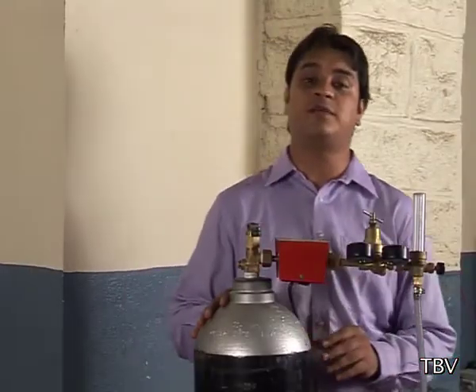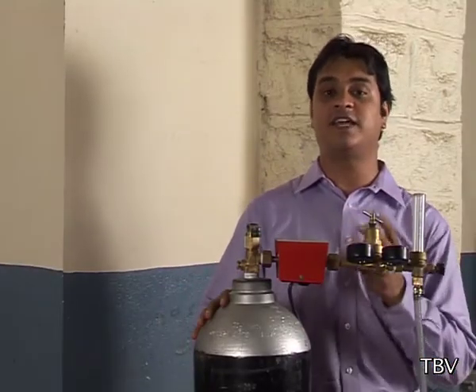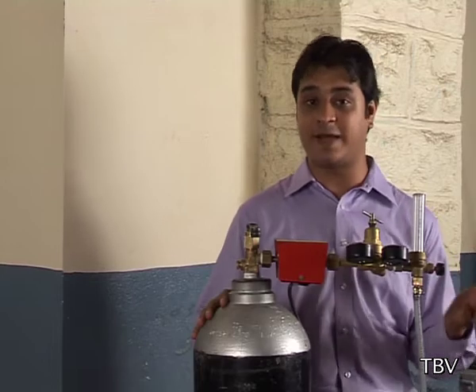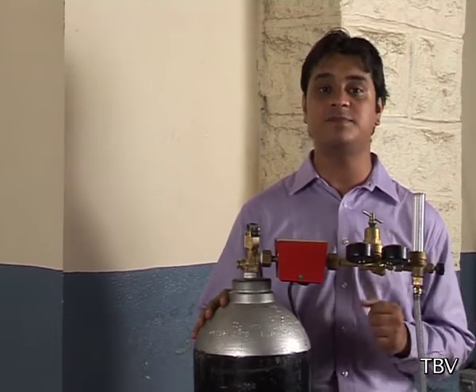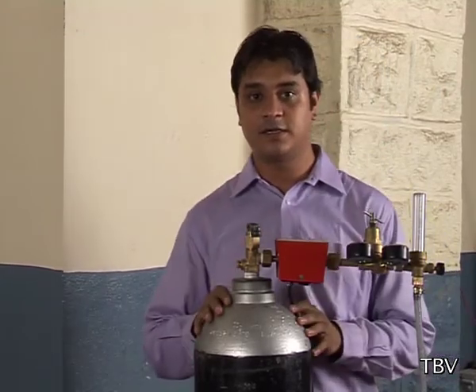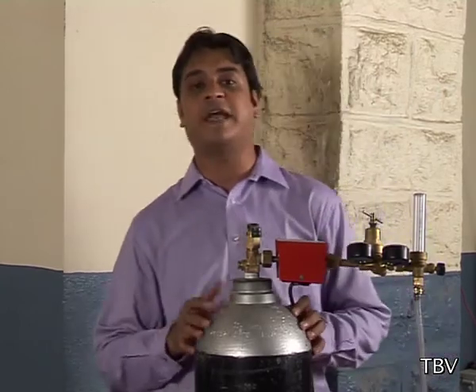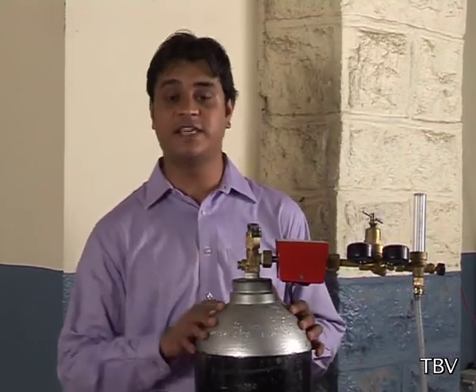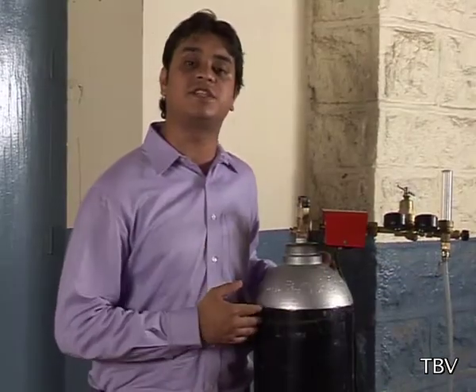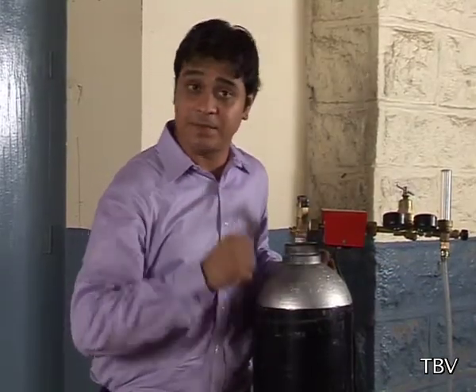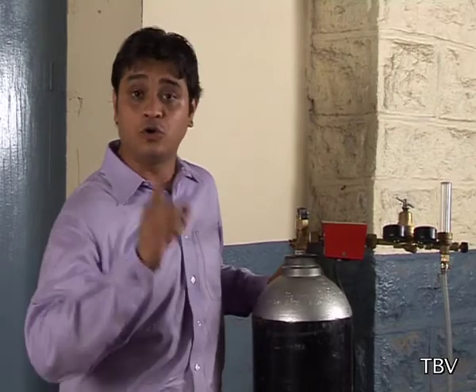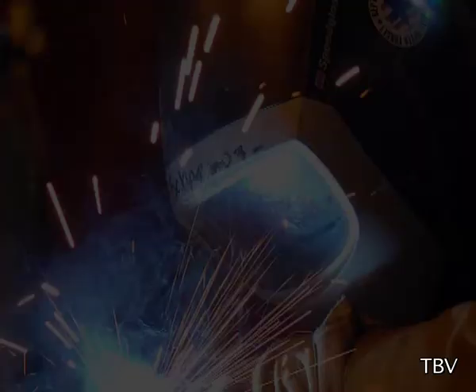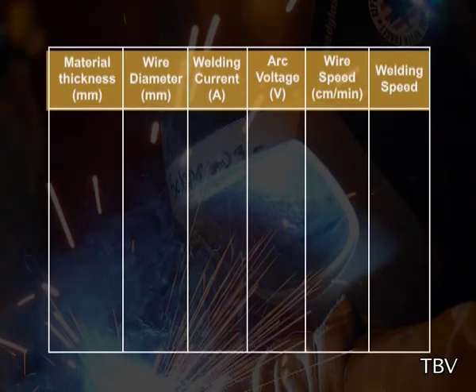Now within the CO2 atmosphere, the arc is very unstable, resulting in excessive spatter. However, this can be reduced by holding a short arc. Deoxidizers like aluminium, manganese and silicon are used. These deoxidizers remove the oxygen from the weld metal. And remember, when using pure CO2, good ventilation is needed. The chart shown mentions the details.